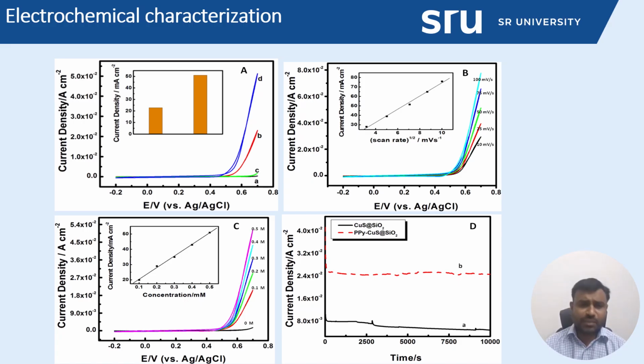Here we can clearly observe that when increasing the concentration, the oxidation peak current of methanol at the PPY copper sulfide hybrid material modified electrode significantly increases, further confirming the good catalytic characteristic of our fabricated copper sulfide polypyrrole hybrid electrodes. It may be noted that when plotting the square root of scan rate versus oxidation peak current, we observed a perfect linearity, because we applied scan rates from 10 to 100 millivolts per second. So the linear plot indicates the oxidation reaction of methanol at the copper sulfide modified electrode is a diffusion controlled process rather than a surface controlled process.